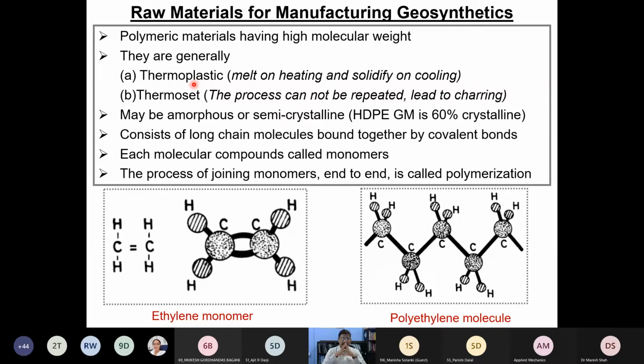These are called crystalline polymers, or semi-crystalline or amorphous. If you look at high density polyethylene, the crystallinity is very close to 50 to 60%. Why are we talking about crystallinity? Because as the crystallinity increases, the mechanical performance of a polymer is also going to vary. Sometimes if the crystallinity increases further, you may go completely from ductile failure to brittle failure. On the other side, from the contaminant transport point of view, if your polymer becomes too crystalline, it is really good because the diffusion through such a polymer is very, very low compared to amorphous polymers.